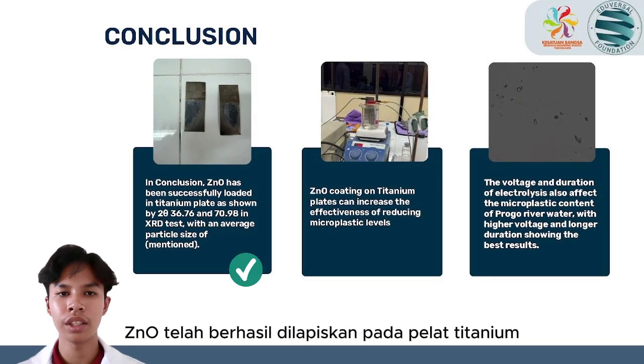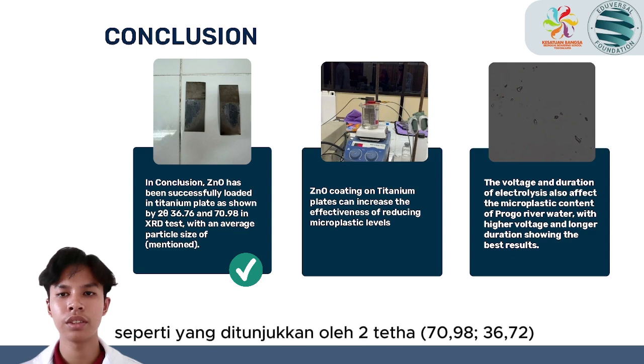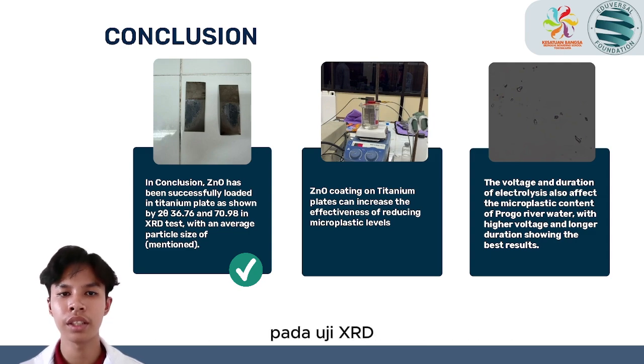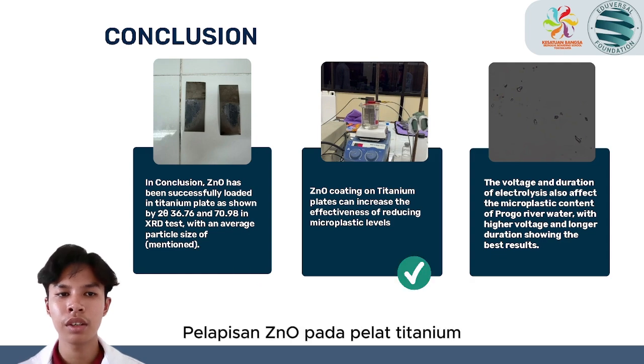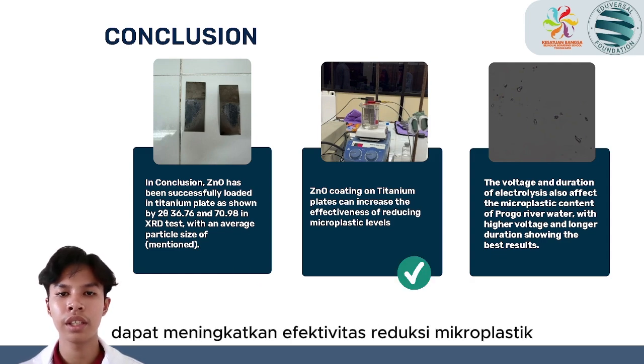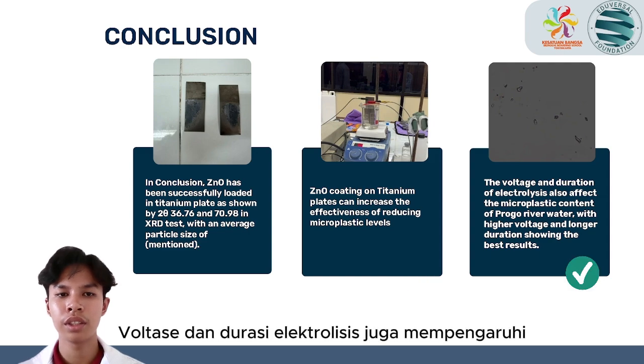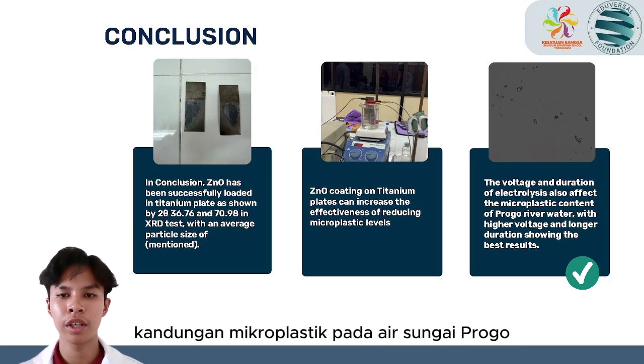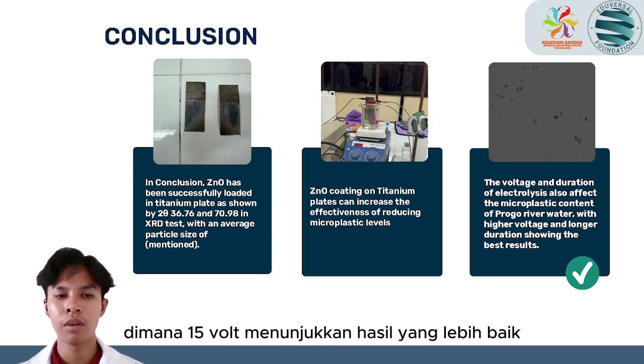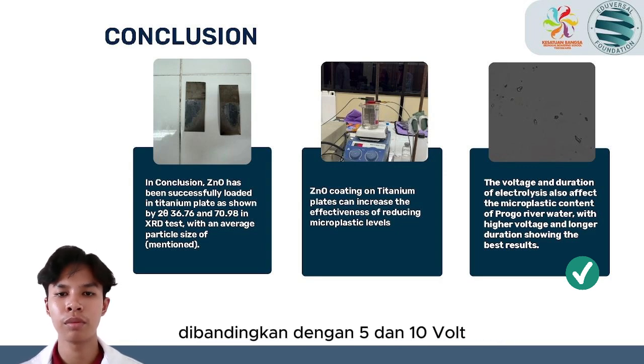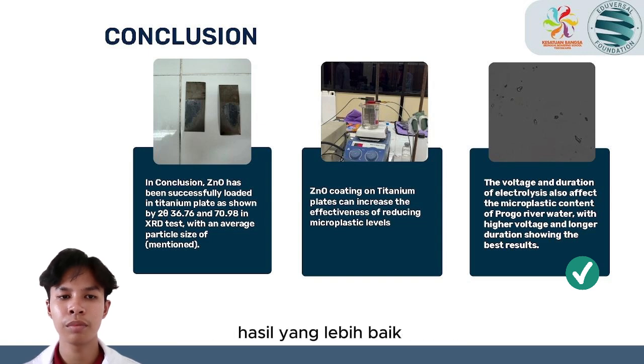Conclusion: zinc oxide has been successfully deposited on titanium plates as shown by 2 theta 70.98 and 36.76 in XRD test, with an average particle size of 37.35. Zinc oxide coating on titanium plates can increase the effectiveness of microplastic reduction. The voltage and duration of electrolysis also affect the microplastic content in Progo River water, where 15 volts shows better result compared to 5 and 10 volt. Duration of 60 minutes also shows better result than 45 and 30 minutes.